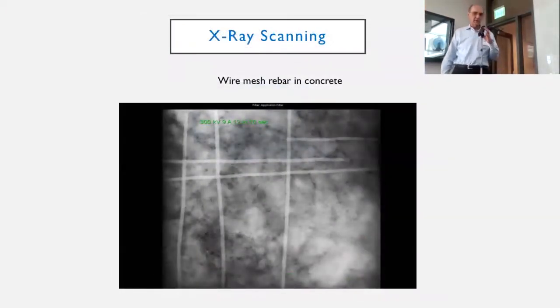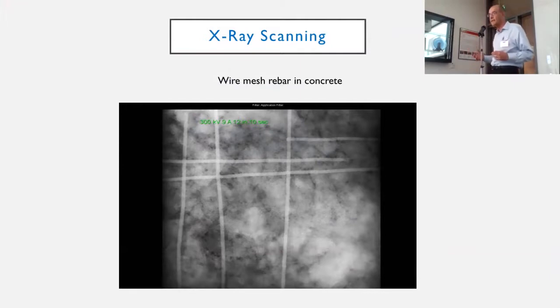Prior to GPR coming onto the scene, which was about 20 years ago, we used to use X-rays to find out where the rebar is in the concrete. This image is of an X-ray. Now, this is X-ray just like you would go to a doctor if you broke a bone or something. And it shows you through the concrete the materials that have higher density in focus. So we've got here steel, steel, steel, crosswise in the center. This shows us where the steel is.